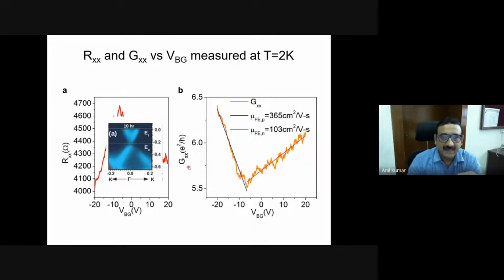And what is happening here? I have this Fermi level. When the Fermi level reaches this point, I am hitting this point, which means the minimum conductance, because the density of states is minimum. When my Fermi level is somewhere here, I have the N-type conducting region. When I bring the Fermi level below this charge neutrality point, I have this P-type region. So by tuning the gate voltage, I am able to make a material P-type or N-type the way I want. That is the beauty of this system.